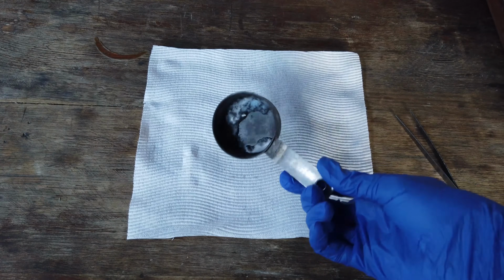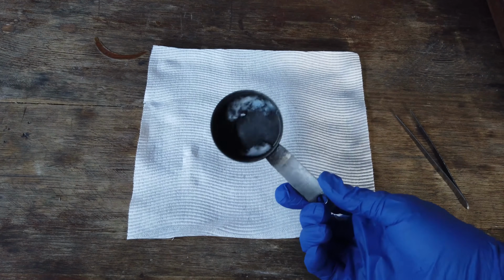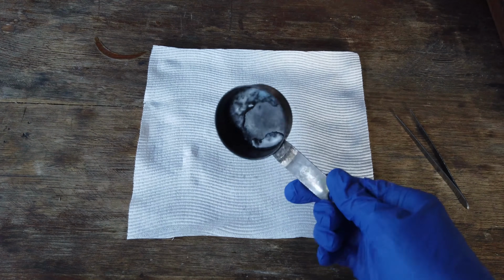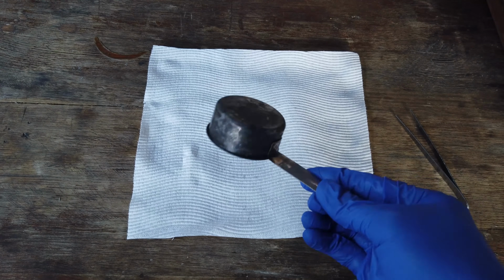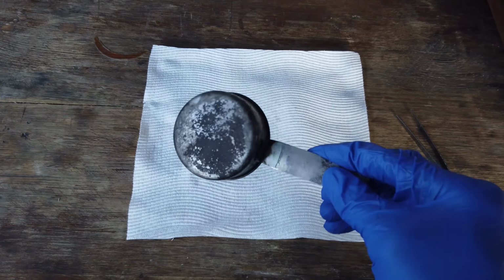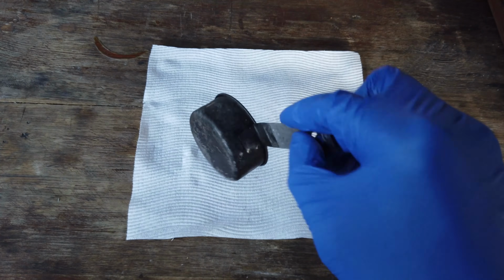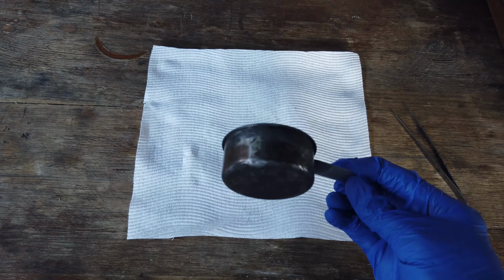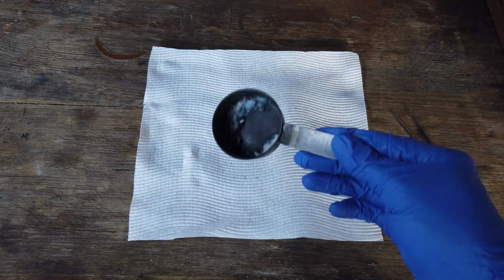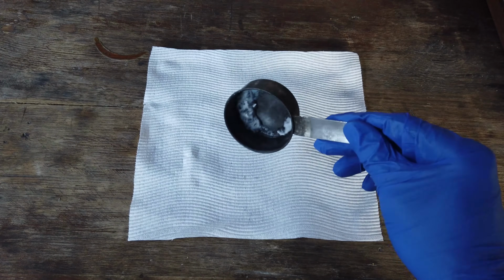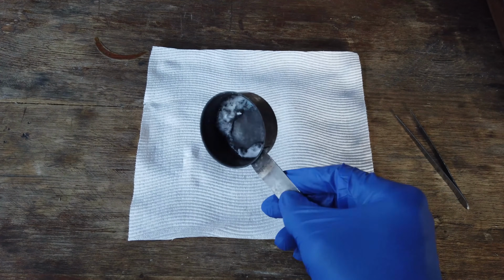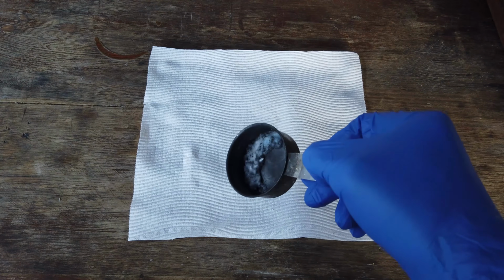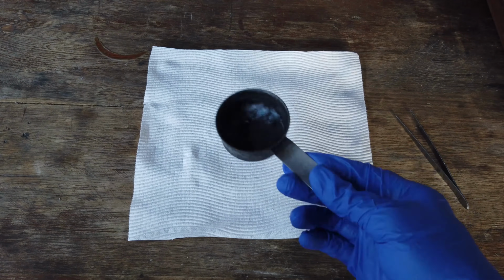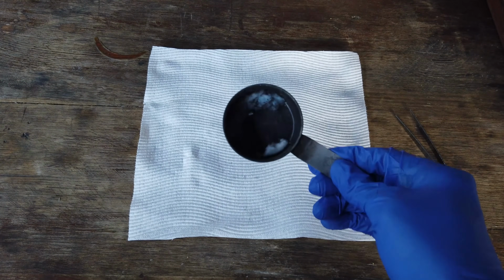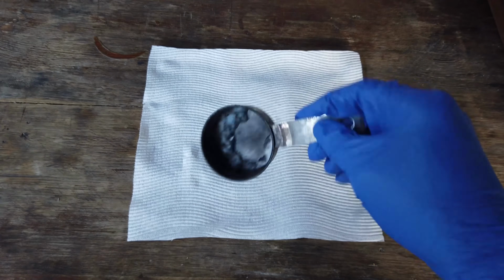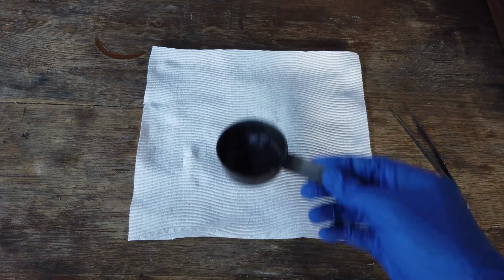We can also see that the stainless steel crucible, the measuring cup that we were using to actually do our electrolysis in, has done remarkably well. If we have a look at that, you'll notice there's a fair bit of oxidation, but really that's just a surface coating. If we really wanted to, we could probably clean that off and the measuring cup would be as good as new. You can see in there's still a little bit of that lithium chloride, potassium chloride eutectic. I've left this soaking in water for about a day and it's nearly finished dissolving it all out, but there's a little bit to go.